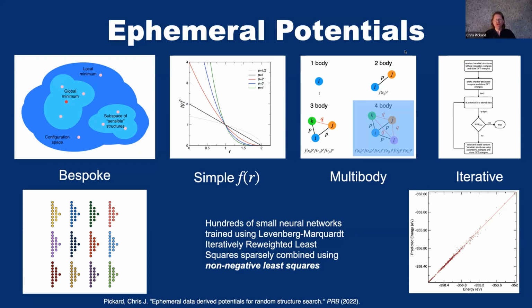So they have a new problem, a new search that they want to do. They want to do a search in a restricted region of configuration space. Well, design a potential that's good for that. Okay, and you can design it as part of the search procedure by doing an active learning scheme where we start by making a potential based on completely random structures, not relaxed at all, but with DFT-calculated energies. We make a first generation of potential, and then we use that potential to do an AIRSS search. Then the structures that result from that search with the first generation of potential, we shake them a little bit, we move the atoms around a little bit, recompute the DFT energies, and then add that to the database of our potential, and then retrain a new potential, go around in a loop, typically 5 times, and then end up with a potential that is converged in some way.